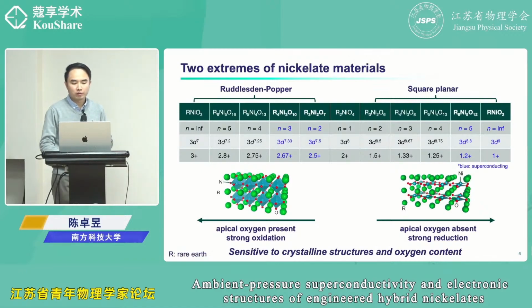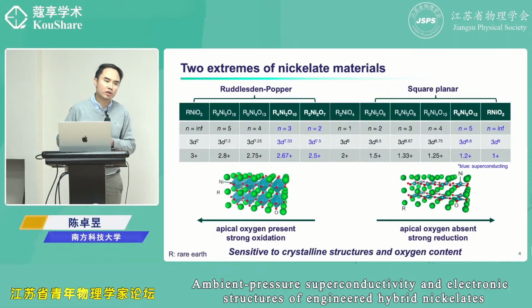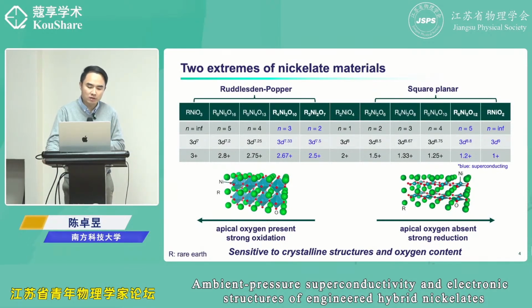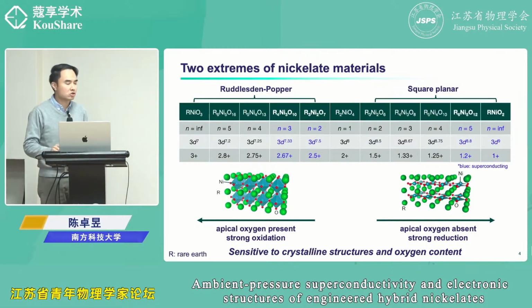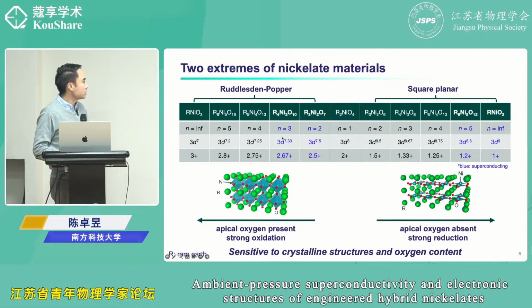Both the fully oxidized state and the state with all apical oxygen removed are not so thermodynamically stable. So for both types of materials, we need to push to a limit that's beyond the thermodynamic stability. So it's very difficult in the sense of controlling oxygen. Another type of difficulty is crystalline structure control. If you look at this whole series, for example, the 4-3-10 structure, the cation ratio between rare earth and nickel is 4 to 3. And the one next to it is 5-4-13, which is a 5 to 4 ratio.